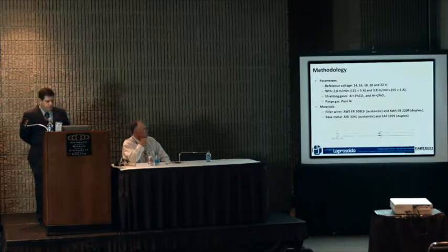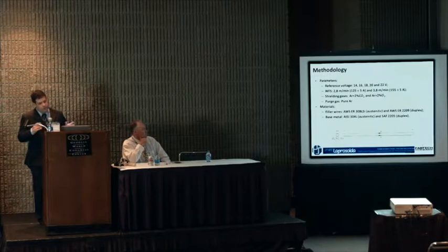Our parameters: reference voltage between 14 and 22 volts, a common range for short circuit transfer. Wire feed speeds of 2.8 meters per minute, which gives us 125 amps, and a second, higher wire feed speed, which gives us 155 amps. This is a conventional constant voltage power source, but it's important in welding that we keep the current as constant as we can. So we change the contact tip to work distance, CTWD, for each wire feed speed. By changing the CTWD during the welding, we keep the wire feed speed and the same current, 125 amps or 155 amps, within a range of 5 amps. So we consider it the same value, from 120 to 130.